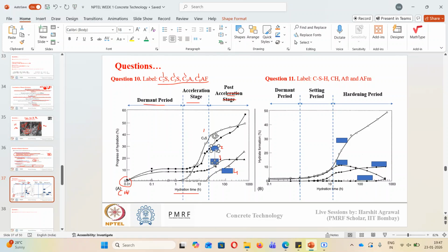Now if you see this curve 2, it has shown reaction from the start, then it remains constant, and then again it increases later on. So this will be C3A.